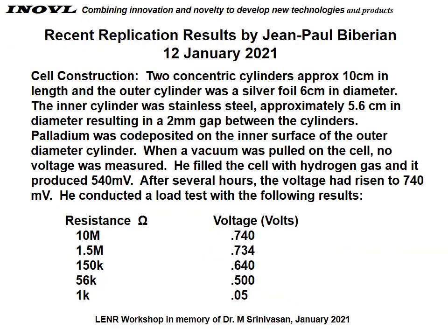Just a few days ago, Jean-Paul Biberian reported some new results. Whereas his first cell had been fairly small, this one was much larger. It consisted of two concentric cylinders, approximately 10 centimeters in length, where the outer cylinder was a silver foil 6 centimeters in diameter. The inner cylinder was stainless steel, approximately 5.6 centimeters in diameter, resulting in a 2 millimeter gap between the cylinders. Palladium had been co-deposited on the inner surface of the outer diameter cylinder. When he assembled the cell and pulled a vacuum, no voltage was measured.